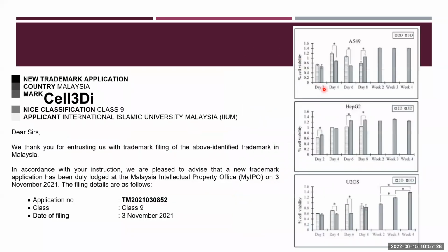So you can find here the cells were actually alive up to 4 weeks. For the first one, used for preserving the cells, the viability is quite high for 4 weeks. Actually, the cells continue to grow, and you can see the viability becomes higher compared to 2D cells. This one we stopped at 1 week because the cells started to overgrow and multi-layer grow. So we stopped after 7 days, and could not proceed. We need to do the maintenance of the cells, change the media, trypsinization and so on. But for 3D cell culture using alginate, we only need to change the media one time per week.